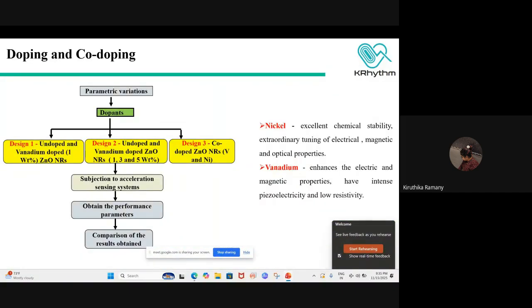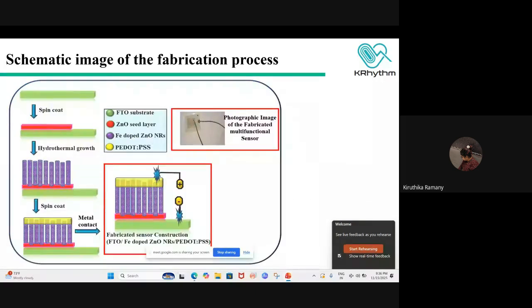The fourth thing was the doping and co-doping concept. First we went for undoped and 1 weight percentage vanadium doped samples. We investigated all the parameters. From this we found that the doped sample had better sensitivity. So we went for 3 varied concentrations, and from that we found that 5 weight percentage of vanadium had better sensing performance. So what we did was combine this 5 weight percentage vanadium and nickel to form a co-doped zinc oxide nanorod. And this is the photographic image of the fabricated multifunctional sensor.